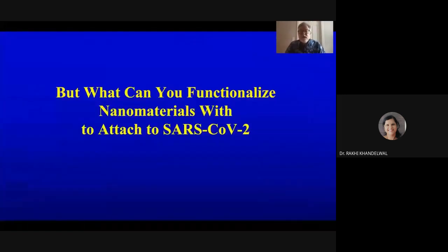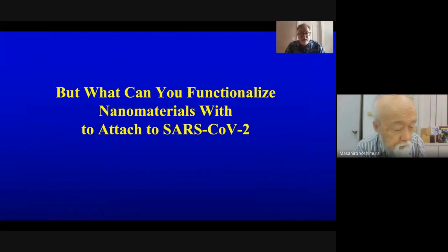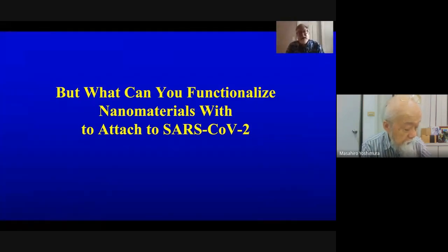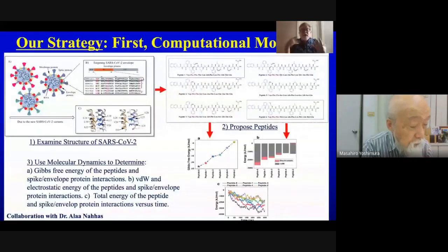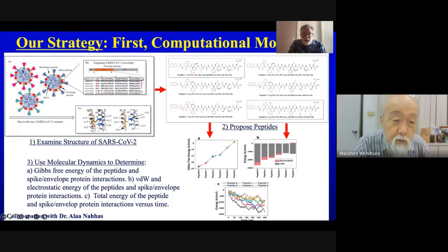So our key question really to ask ourselves around 2019, 2020, when we wanted to contribute to materials that could passivate SARS-CoV-2, is what do we functionalize this molecule with? As I showed you, lysine was the amino acid we used for tissue engineering. We wanted to replace that and use a new peptide that could attach to SARS-CoV-2. The other thing that we wanted to do is we knew from virus research that the spike protein in SARS-CoV-2 was going to mutate. In fact, all of the variants that have occurred since the original Wuhan strain of SARS-CoV-2 involves mutations in the spike protein. So many groups target the spike protein, but we didn't want to because we knew it would mutate. And if it mutates, then the peptide we developed to attach to it is no longer worth its weight.